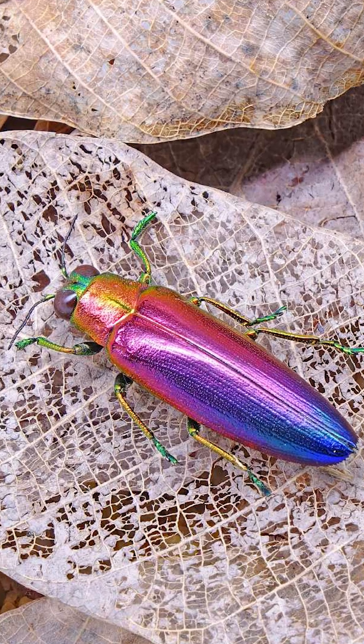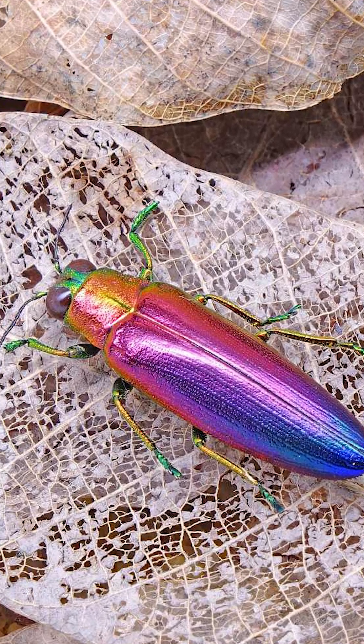You can also find structural colors in seashells like Mother of Pearl, where its iridescent shine comes from a brick-and-mortar structure of calcium carbonate layers that are just 400 to 600 nanometers thick. And look at this jewel beetle — its colorful shell comes from twisting multi-layers that reflect only one kind of circularly polarized light, just like 3D glasses.